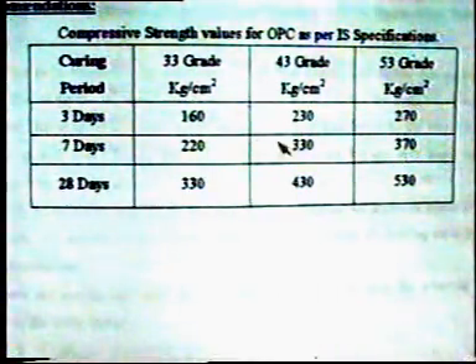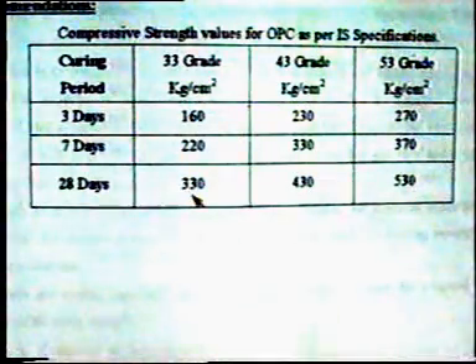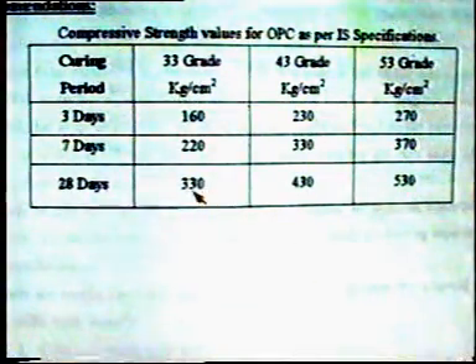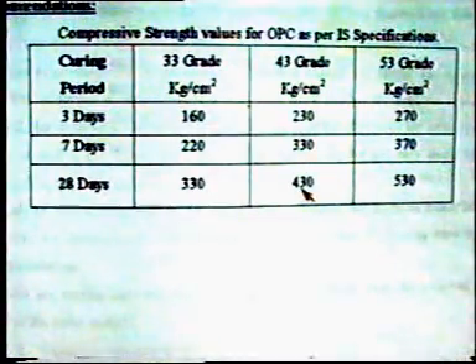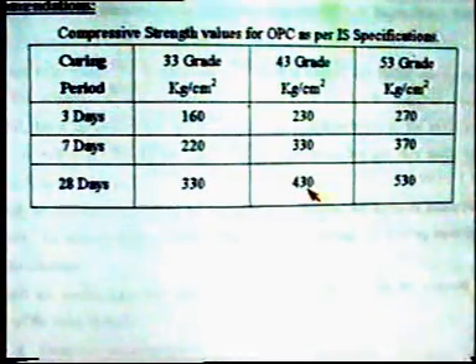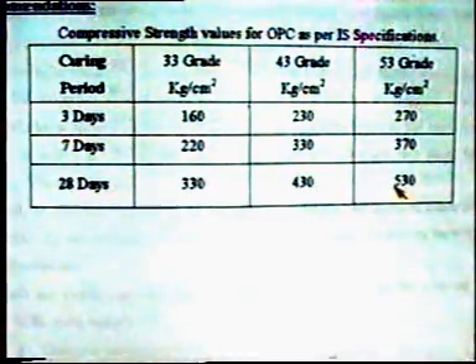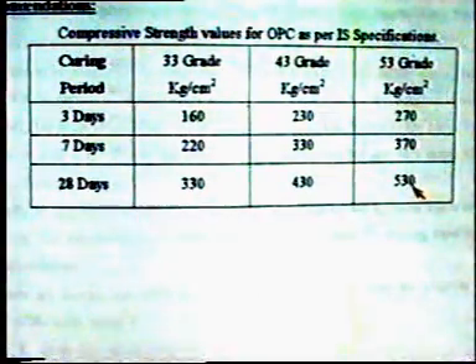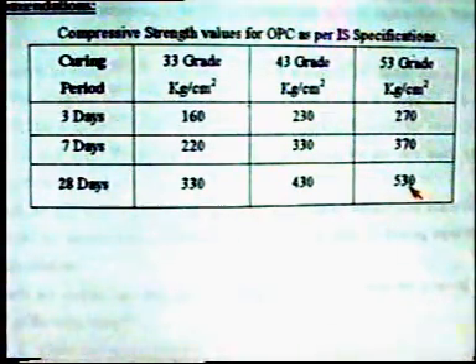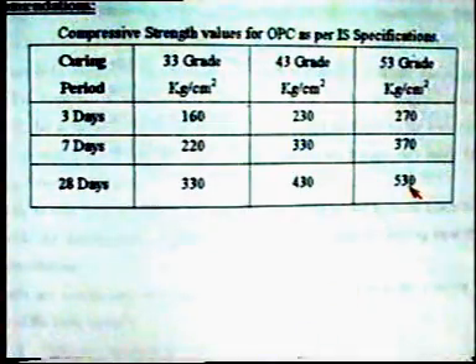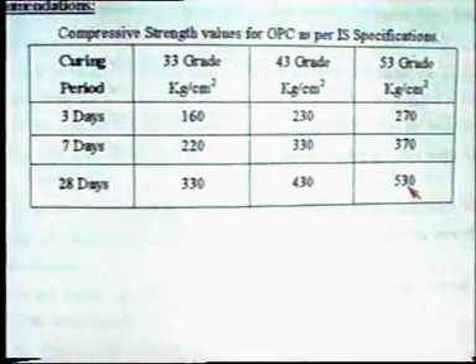On 28 days curing, it should not be less than 330 kg per centimeter square for 33 grade cement, 430 kg per centimeter square for 43 grade cement, and it should not be less than 530 kg per centimeter square for 53 grade cement as per the IS specifications as you see in the table now.